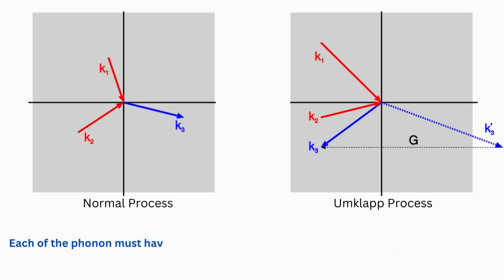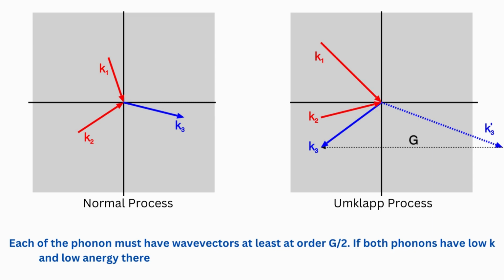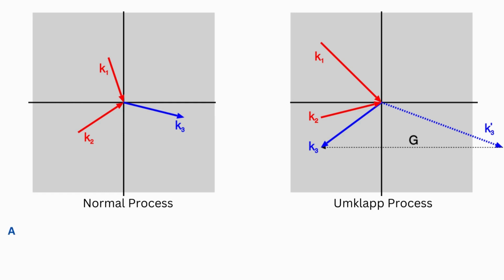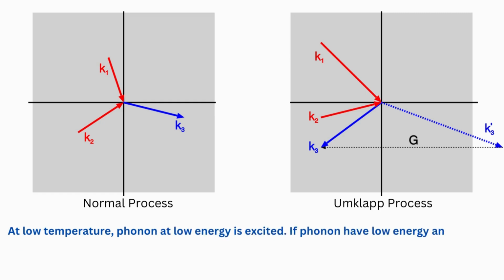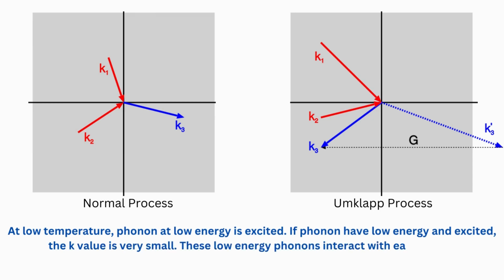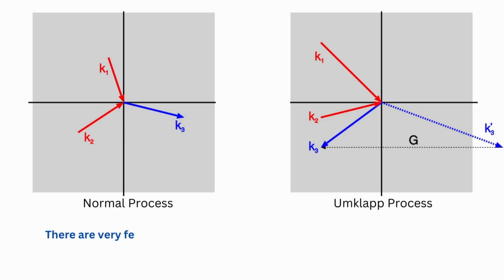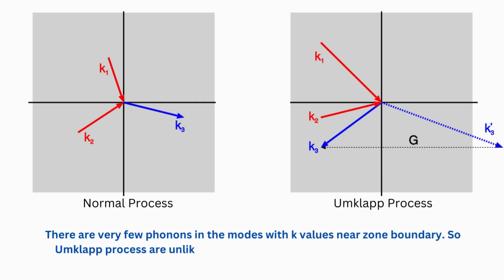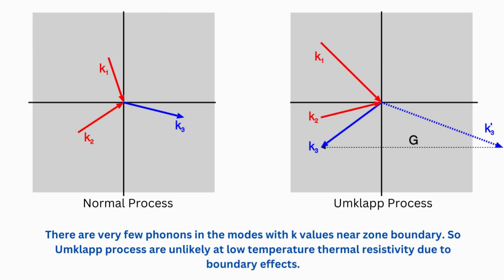Each of the phonons must have wave vectors at least of the order g over 2. If both phonons have low k and low energy, there is no way to get a phonon outside the first Brillouin zone from a collision. At low temperature, phonons at low energy are excited. If phonons have low energy, the value of k is very small. These low energy phonons interact with each other. There are very few phonons in the modes with k values near the zone boundary. So Umklapp processes are unlikely at low temperature; thermal resistivity is due to boundary effects.